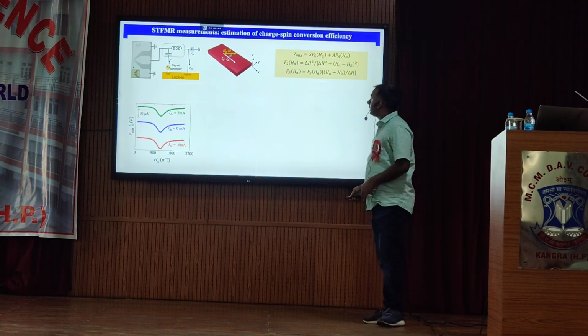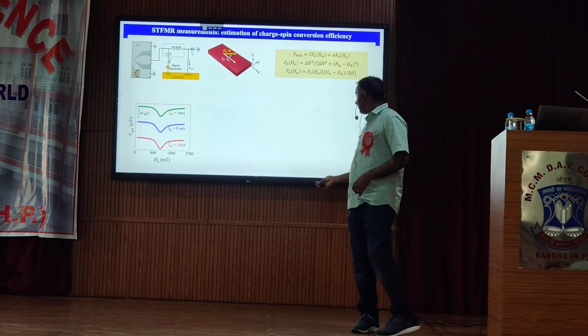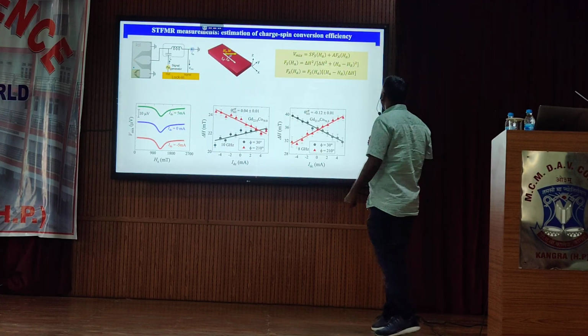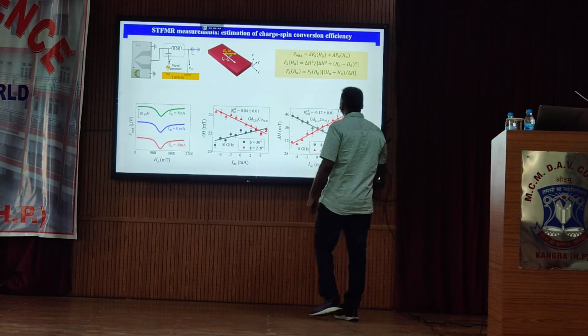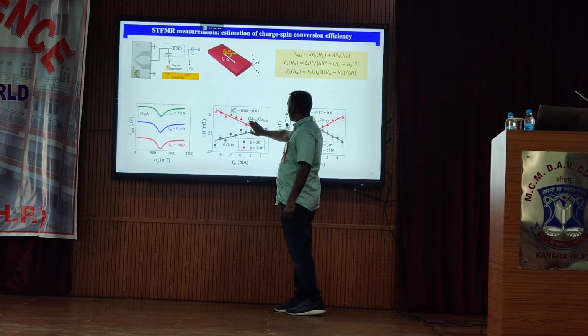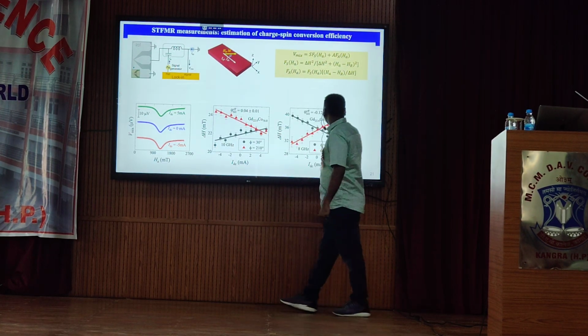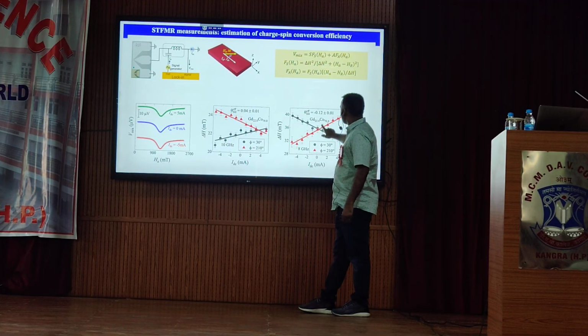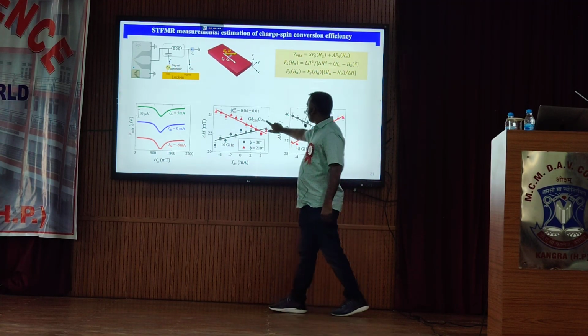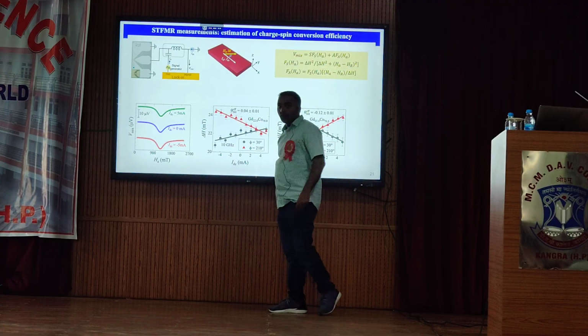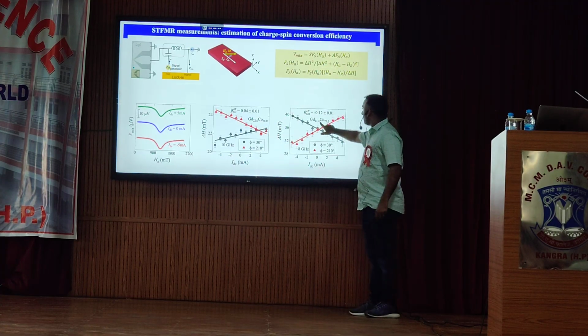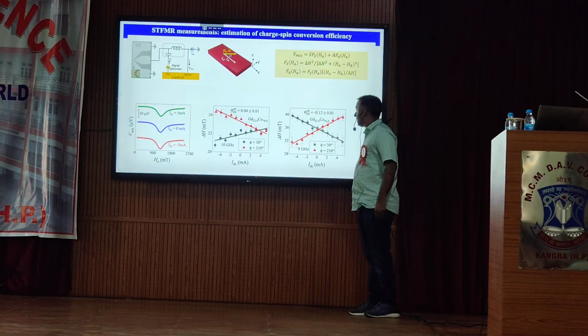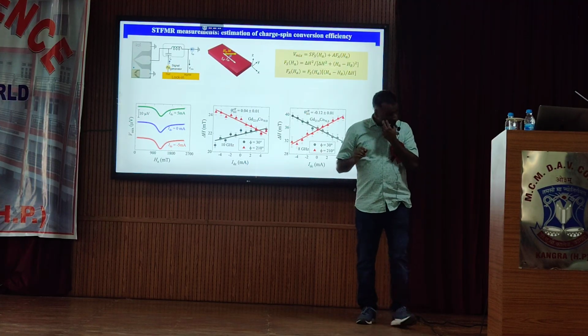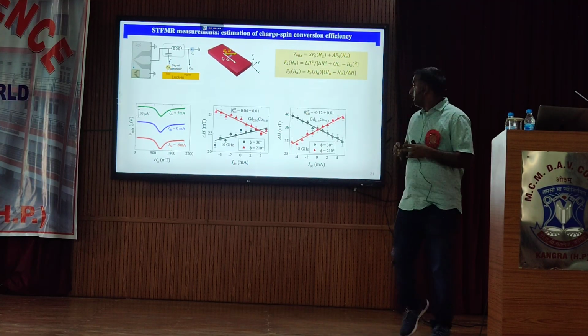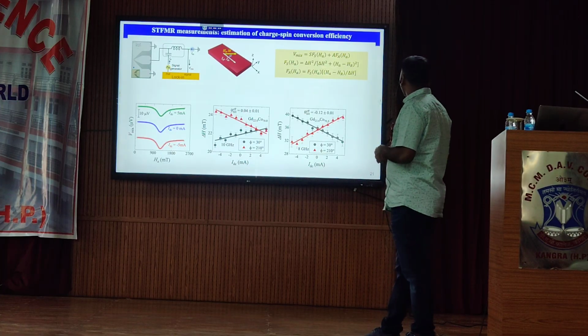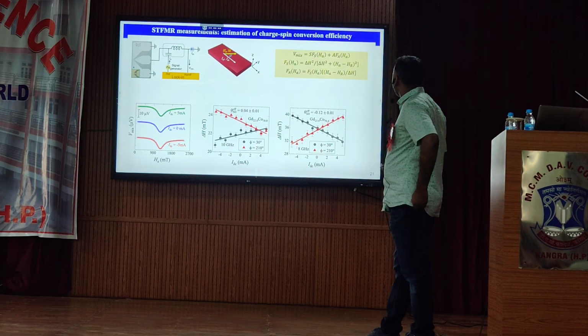So the results of the ST measurements can be seen here. For these samples also, we see very interesting properties. For the different compositions of gadolinium cobalt, you will see different amplitudes of the spin orbit torque efficiency. For 22% of gadolinium, we have a positive spin Hall effect. For 23.4% of gadolinium, we have a negative spin Hall effect. So we see a transition in spin Hall conductivity when we change the composition of gadolinium cobalt, which is also very interesting for our application.